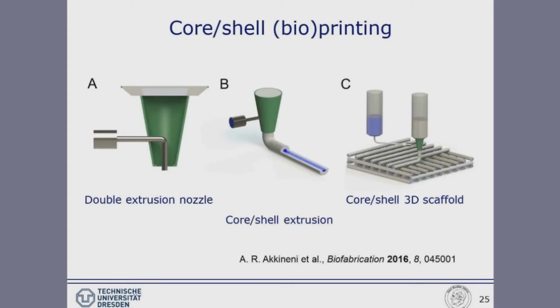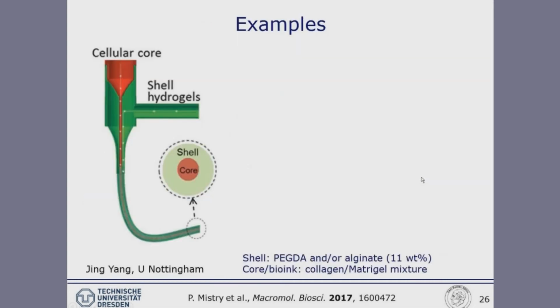Also, my group is working in this field, so this schematic has been taken from a paper we published last year on core-shell printing. Only a little bit of bioprinting is included here. So of course you need a double extrusion nozzle, which then is connected to two reservoirs, two syringes of your printing device, so that you can extrude two materials simultaneously, shown schematically with the blue and the gray color. And if you mount this to your 3D printer, you can make scaffolds out of this.